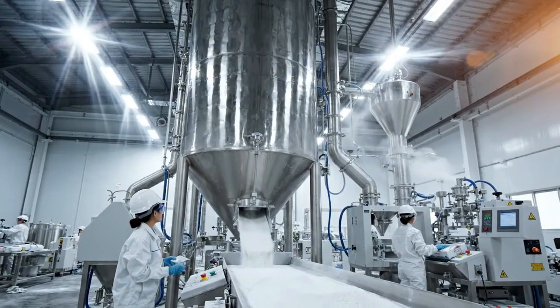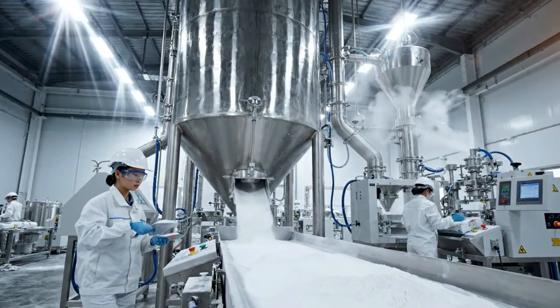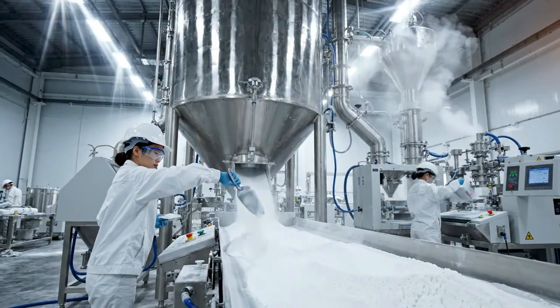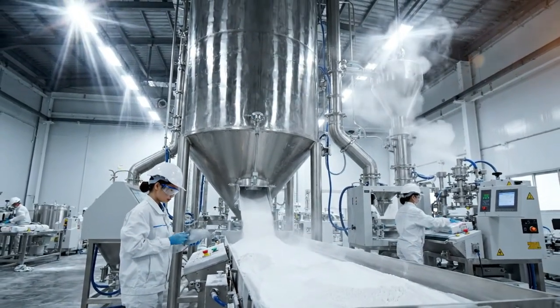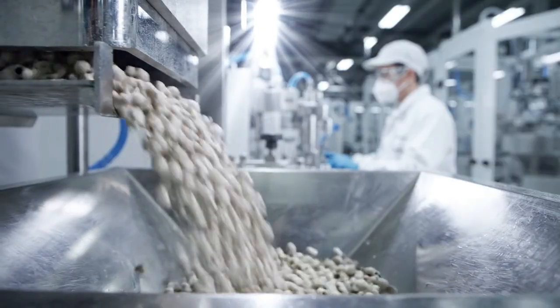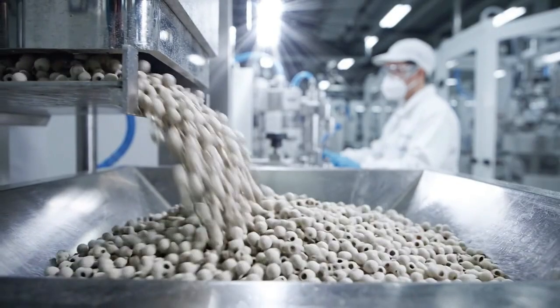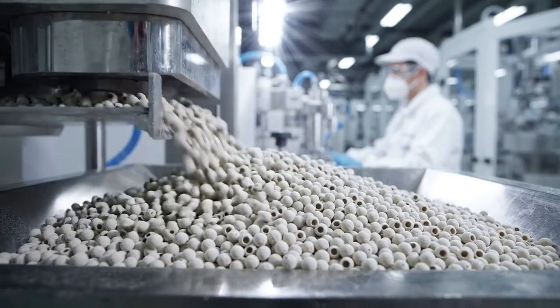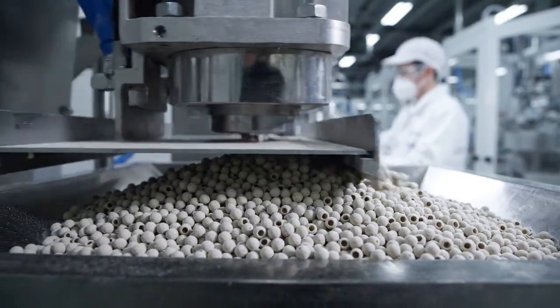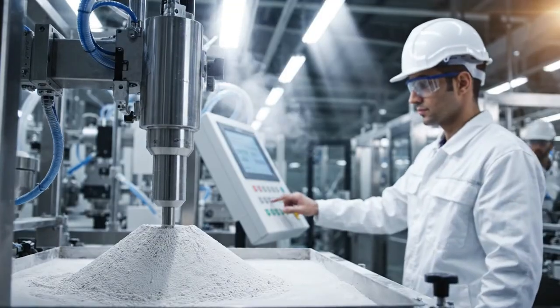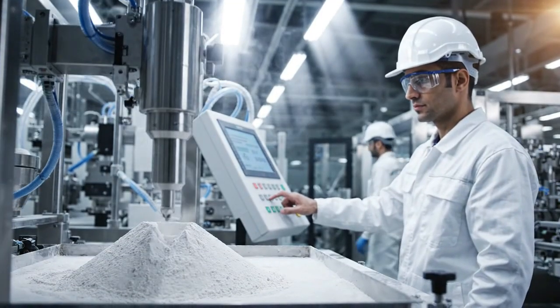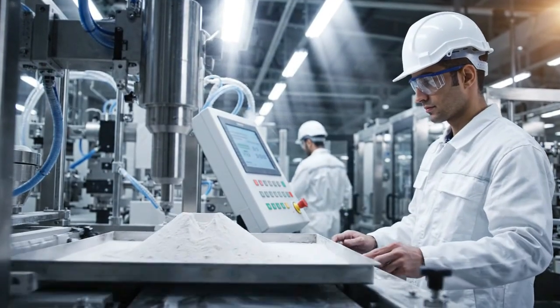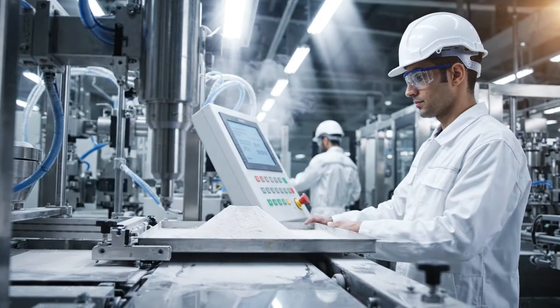Each spray-dried granule is a perfect sphere about 0.5 millimeter in diameter. This uniform shape enables consistent die filling and produces tiles with uniform density. Moisture content must be precisely controlled between 5 and 7%. Too dry and the tile cracks during pressing. Too wet and the tile sticks to the die.